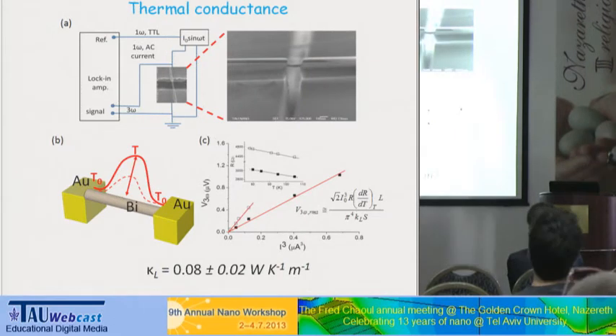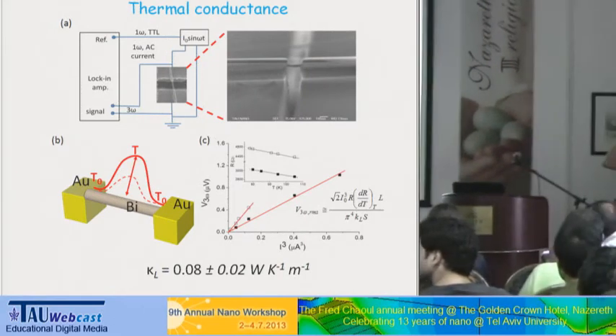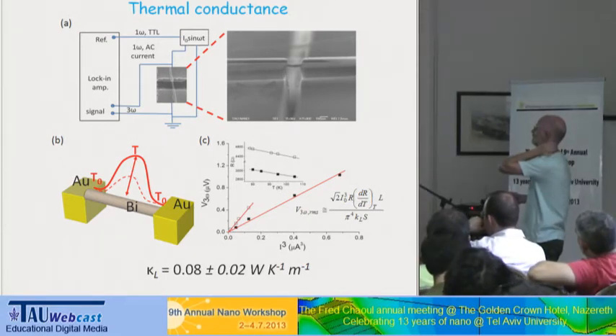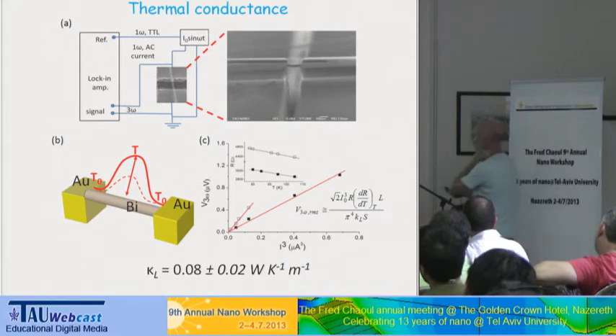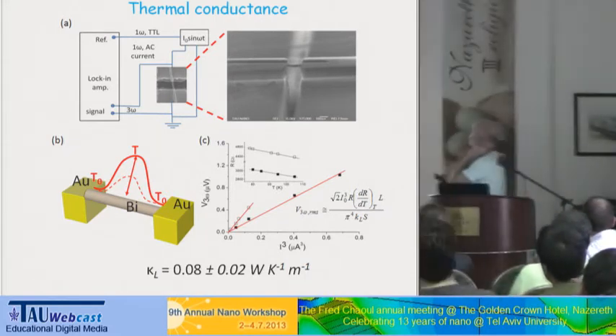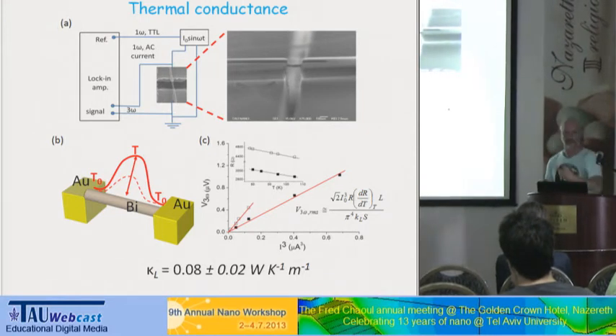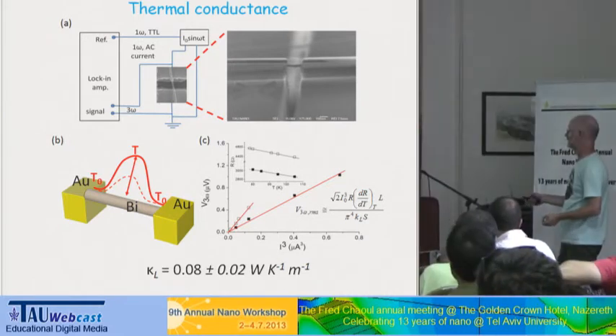So how do we solve the problem of measuring the thermal conductivity? We made a structure which is suspended. Here's the wire above a certain gap inside the structure, and you have contacts on both sides. What we do is the following. We put an AC current flowing through the wire. There's heating taking place due to the flowing of the current. So the temperature gradient is what you see here. It's higher in the middle, it's lower at the edges, and it is fluctuating up and down.